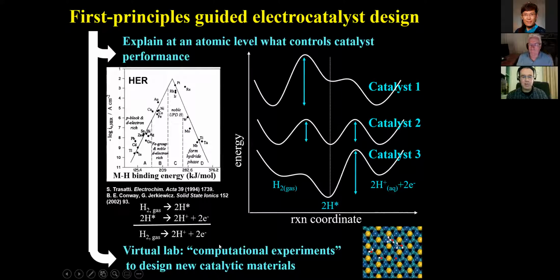Now we can use these same equations because they did not require the experimental data to parameterize. We can use our computational chemistry to run design experiments where we change the atoms around. In other words, convert a platinum atom to a gold atom or mix 3 different atom types together and see how that changes how strong hydrogen binds to its surface, or if it's a more complex reaction, the stability of various intermediates. And of course, we can do that quickly because all we have to do is go into a file and change platinum to gold by changing where it says PT to say AU. So we can do that quickly. We can screen, or we can just evaluate, or we can hypothesize a metal composition that might be better and get an answer relatively quickly.